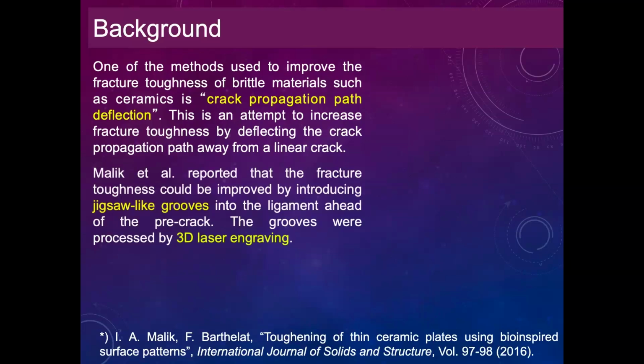Malik reported that the fracture toughness could be improved by introducing jigsaw-like grooves into the ligament ahead of the artificial crack in the CT specimen. The grooves were processed by 3D laser engraving.